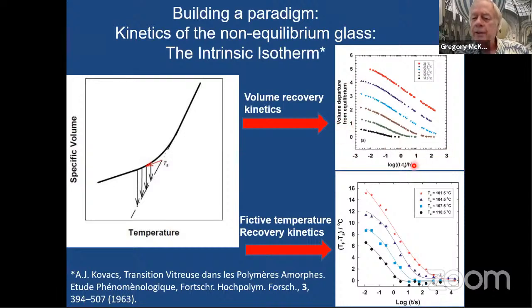And here it's log time, and this T minus Ti has to do with how long it actually takes to change the temperature. And these are at different temperatures. This was a polyvinyl acetate glass. And what you see is when you're at high temperature, so at 37.5 degrees, it's taking maybe a half hour or something to get into equilibrium. But as I go to lower temperatures, and that's at 25 degrees, this one, you can see that in over 100 hours, it's not even close to equilibrium.